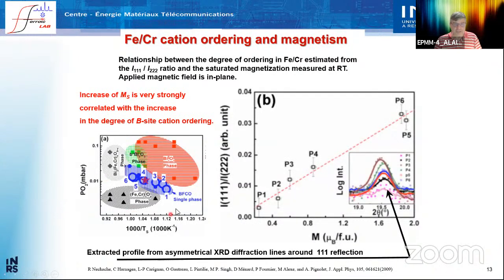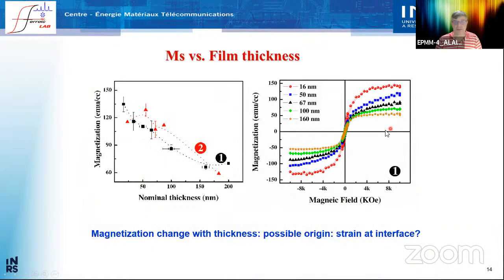This is a phase diagram, so of course we have a very narrow window, the blue region, in which things are working, and depending on the exact synthesis conditions, you have a different cation ordering, as you can see here as well. And this cation ordering also depends on the thickness. As the film grows thicker, cationic ordering is decreasing.